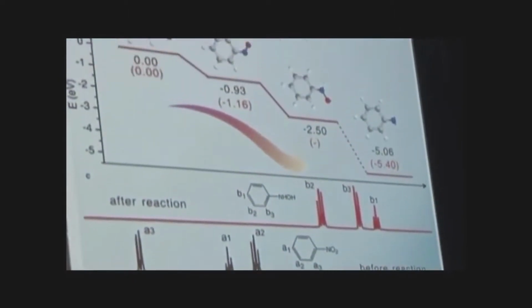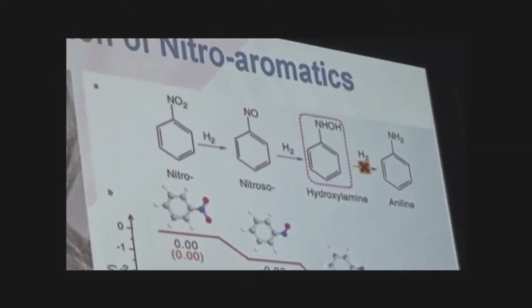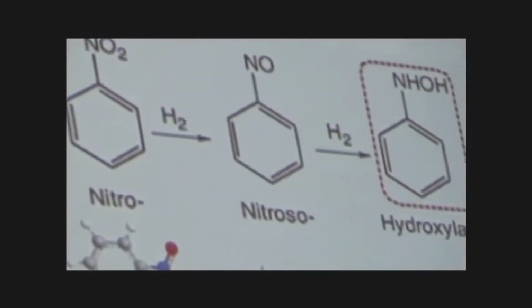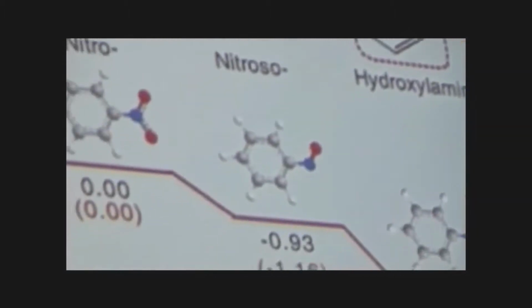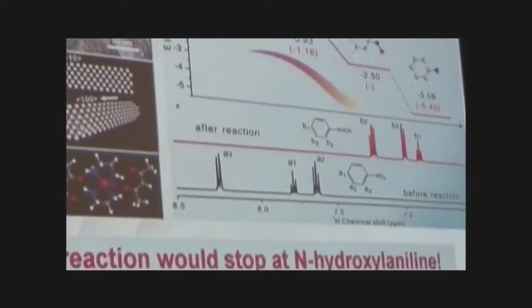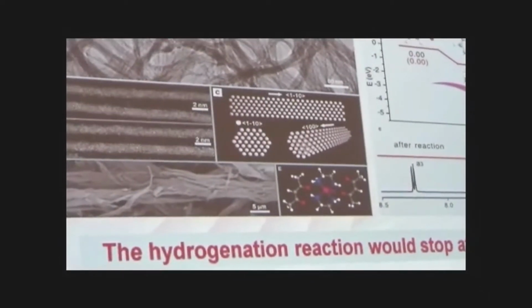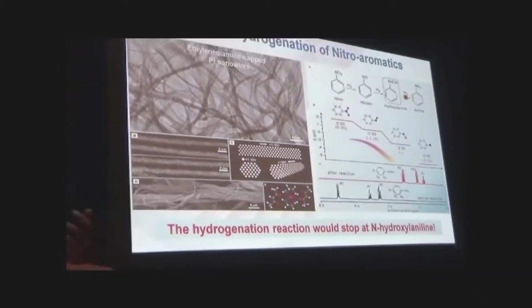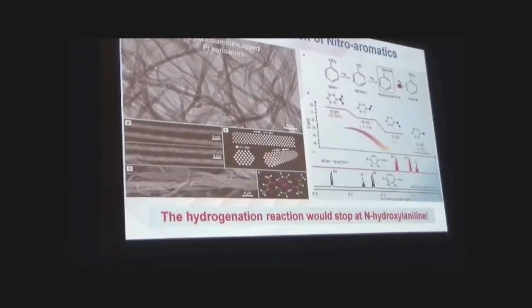So the second example is the selective hydrogenation of nitrobenzene. As you know, the final product of the hydrogenation of nitrobenzene is aniline, because from the viewpoint of thermodynamics, the most stable hydrogenated product is aniline. However, when we use the ultrathin Pt nanowire established here, the main product is not aniline, it's hydroxylaniline. So the selectivity to the unstable partially hydrogenated product is very strong. Why?